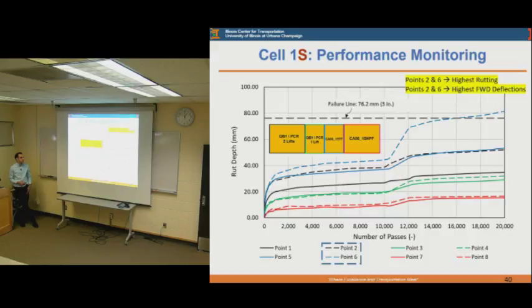In the other 2 of them, they were less consistent, and there was more variability between the 2 measuring points in each section. But overall, all the rutting in these sections was following the trend of the FWD measured on top of each point before the trafficking of the test sections.